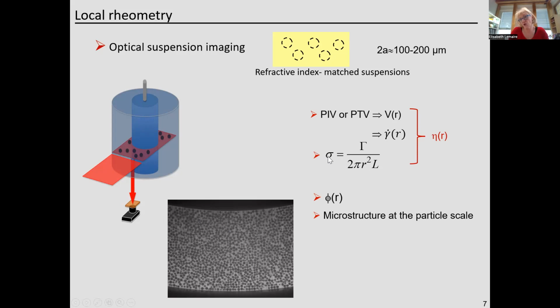Well, it gives us the shear stress everywhere in the gap. So we have the shear rate and the shear stress, so we can measure locally the viscosity. And with this technique, we can also measure the distribution of the particles, so we can measure the concentration field. And also, we can measure the microstructure at the particle scale.